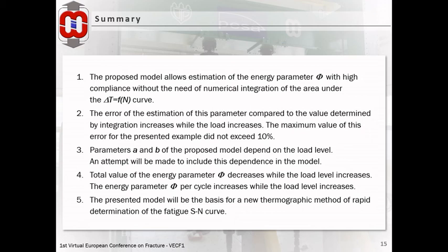Parameters A and B of the proposed model depend on the load level. An attempt will be made to include this dependence in the model. Total value of the energy parameter decreases while the load level increases. The energy parameter per cycle increases with the load level.